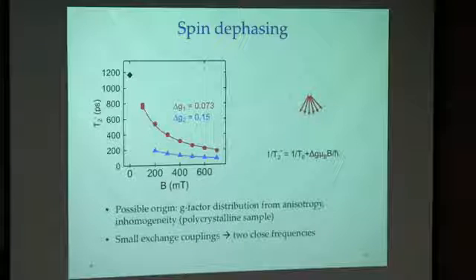But I don't really use that as the spin decoherence time because it's not a direct measurement. It's like a fitting, assuming the dephasing only comes from the G factor distribution, but it may not be true. But if we really like to infer a spin decoherence time, say this curve extends to something over 1 nanosecond at 0 field.